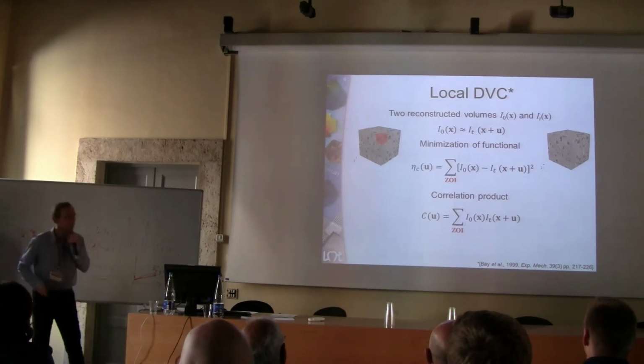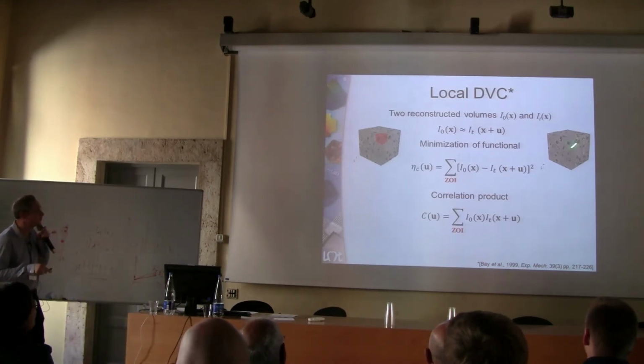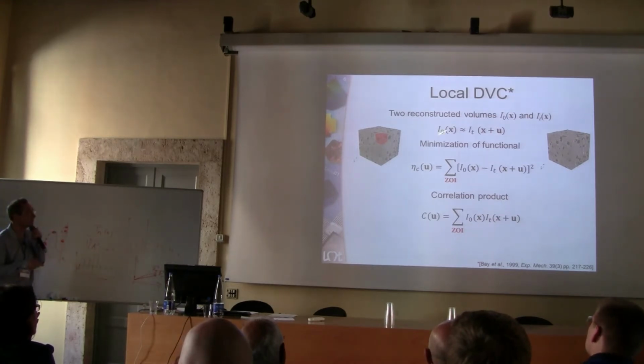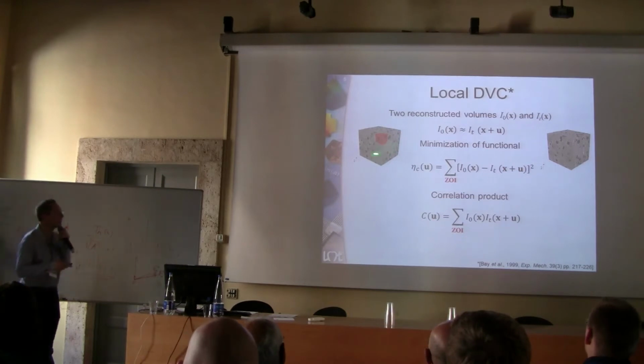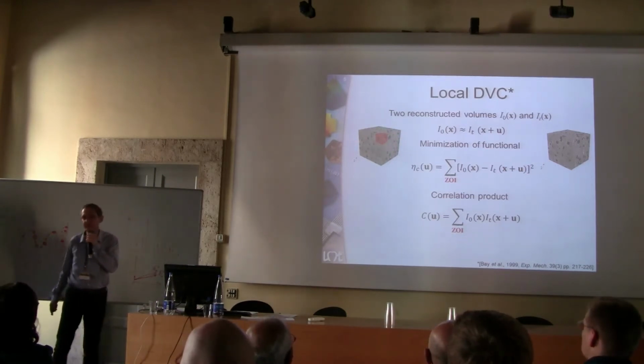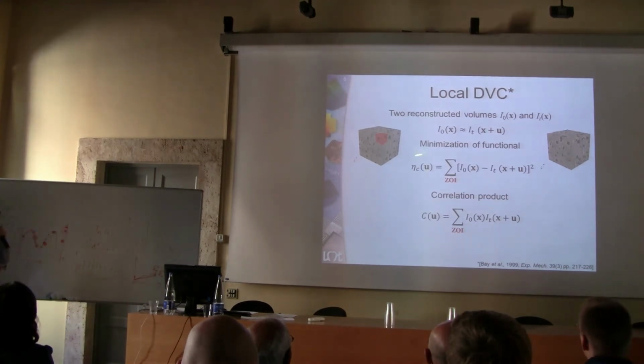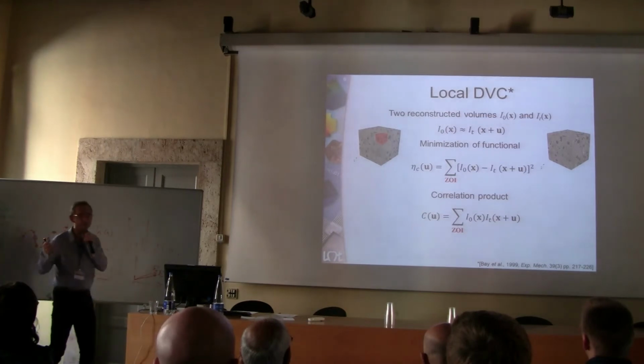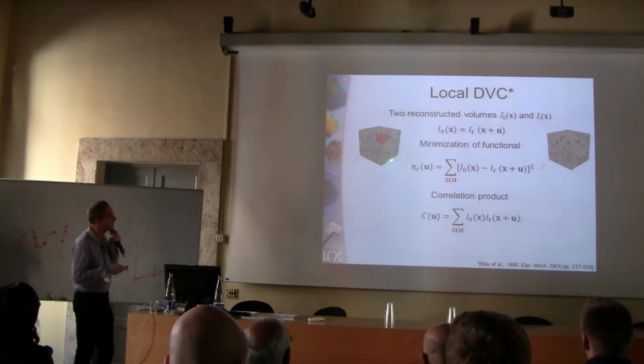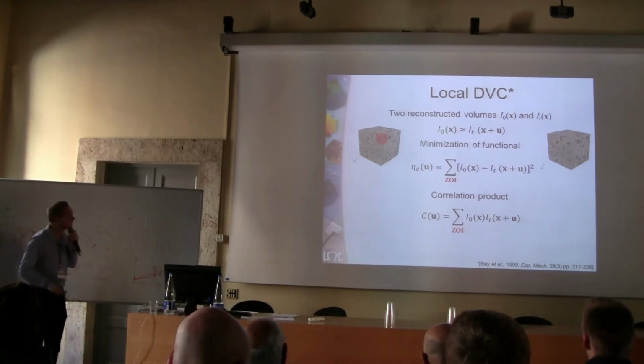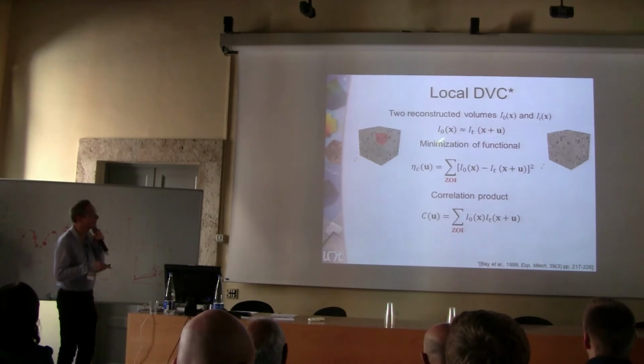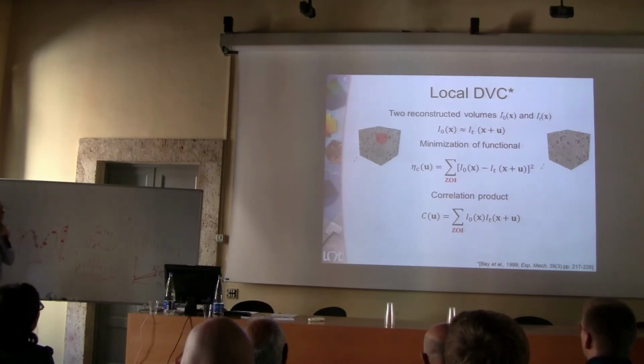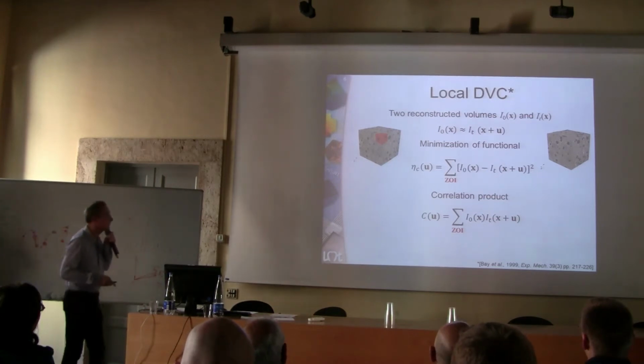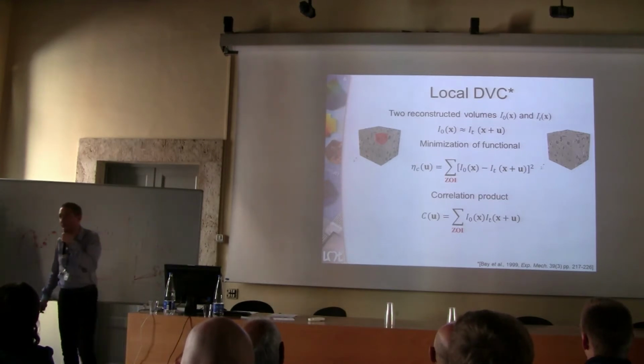The very simple scheme is to consider two reconstructed volumes, one in the reference configuration, one in the deformed configuration. You subdivide the volume into small interrogation volumes, and you want to determine the mean translation that occurred for each small interrogation volume between time 0 and time t. If everything were perfect, the gray levels at voxel location x would have moved to x plus u, so you try to determine u by minimizing the sum of squared differences with respect to your unknown translation.